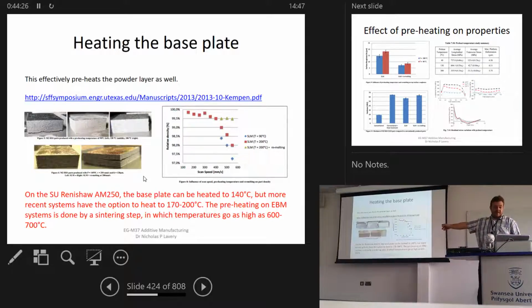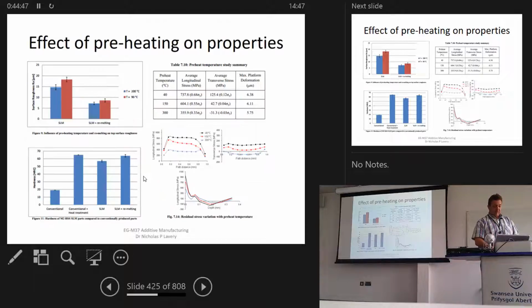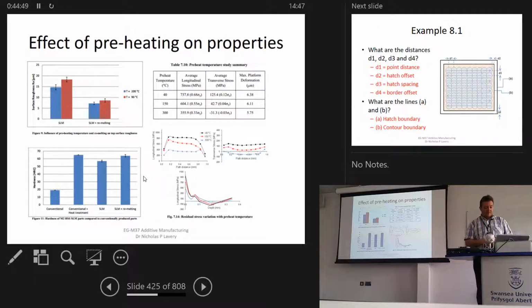It does actually affect the density itself. So you can see here some experimentation where the scan speed has been varied, but also whether or not the plate is heated. And you can see that especially at the higher line speeds, the preheating of the plate allows you to have higher densities, which are up in the 99.5% area. They do have an effect on residual stress.